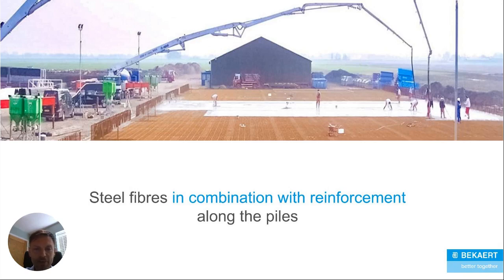This is the system that we've had for a couple of decades. Traditional mesh throughout, however, reduced by anything from 40 to 60% over what it would need to be if it was fully traditionally reinforced. So you can see that's fibre reinforced concrete being pumped to the workface over the mesh.